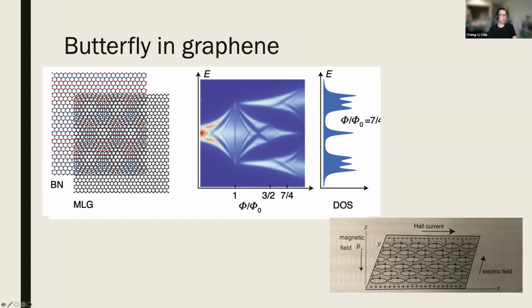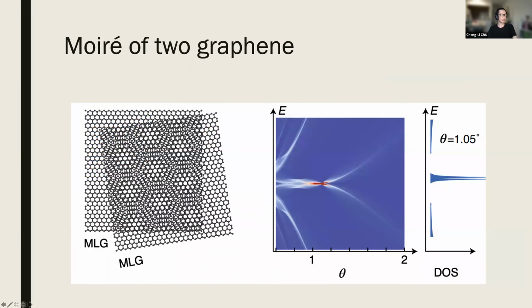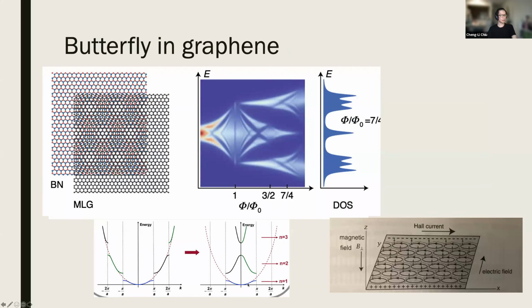So this created a new field for people to study how graphene behaves under a magnetic field with this Moiré pattern. But another way to create a Moiré pattern is just by stacking two graphene layers together. If you step back, you can see that there's a larger periodicity on top of the original graphene periodicity. So the similar thing can happen in this type of system. You add an additional periodicity onto your original Dirac cone. What's going to happen is that you will basically cut your Dirac cone into many little pieces and then open up a gap at the boundary.